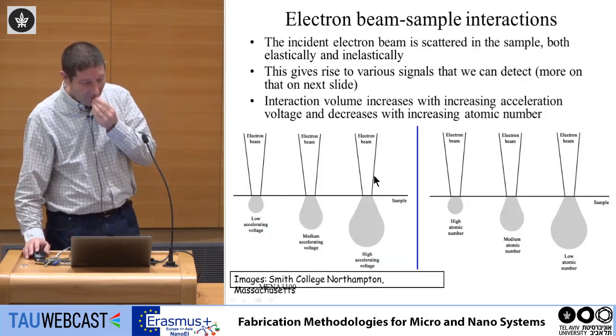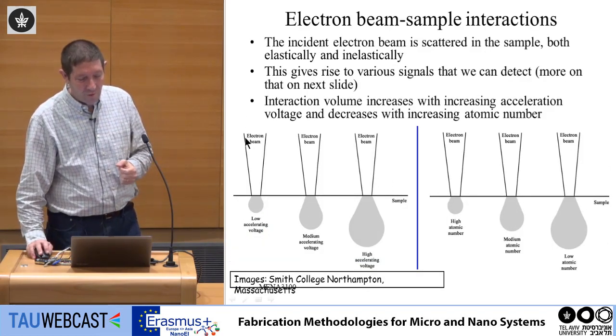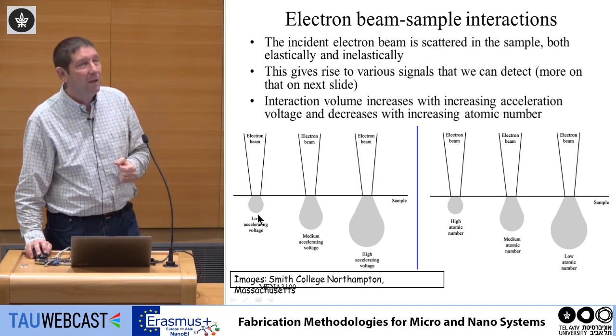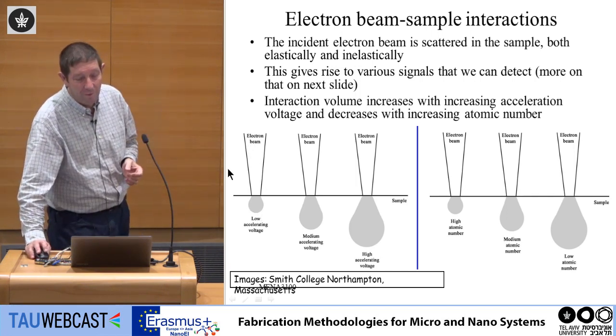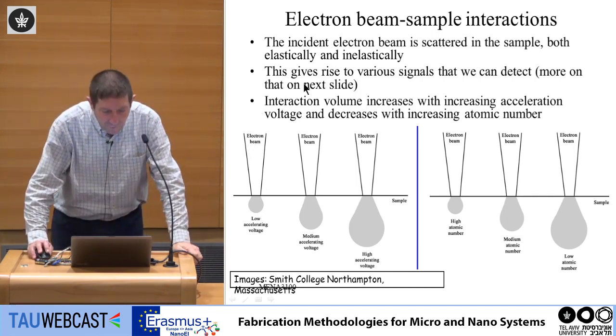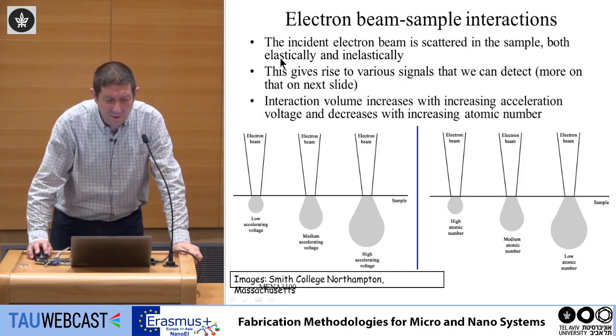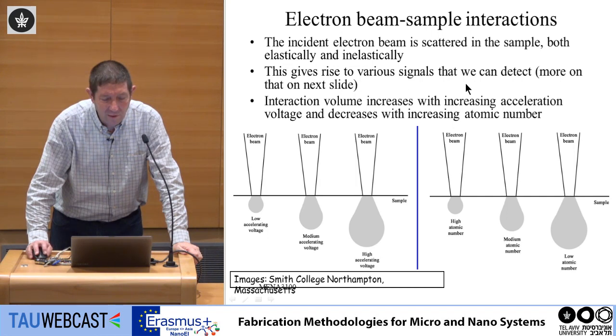Now, the problem is not a problem, but you have to understand the mechanism of interaction between the electron beam and the substrate. This is also relevant for TEM. So what happens when the incident electron beam is scattered in the sample, both elastically and inelastically? This gives rise to various signals that we can detect.